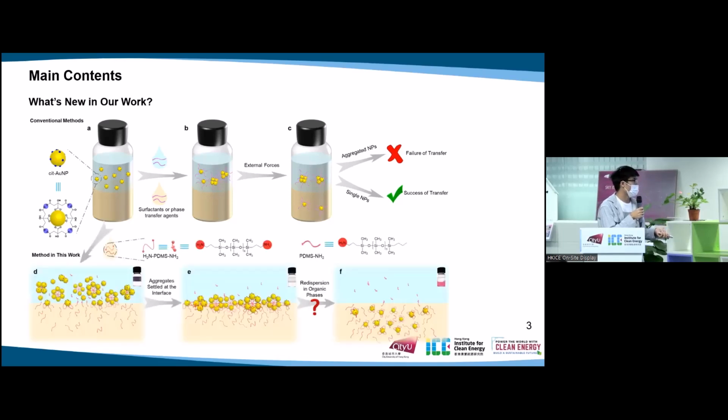In our work, however, by using amino-terminated PDMS as the ligand, the transfer process undergoes nanoparticle aggregation in the aqueous phase, then sedimentation of these aggregates at the interface, and finally redispersion of the nanoparticles in the organic phase.